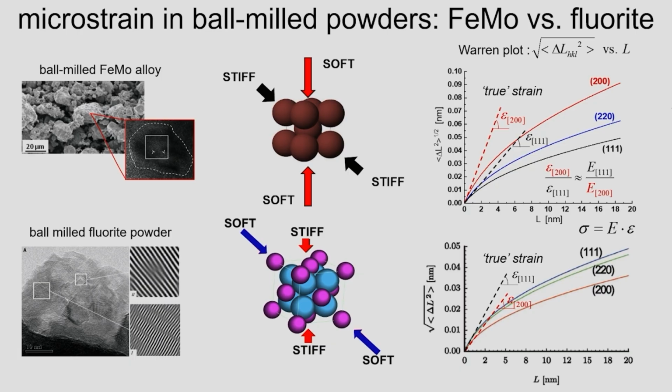So the product is a constant. From the ratio between the strain, you can get the inverse ratio of elastic constants. Is this interesting? Yes, because from this anisotropy, I will show you how you can estimate the yield stress of the material and the resilience.